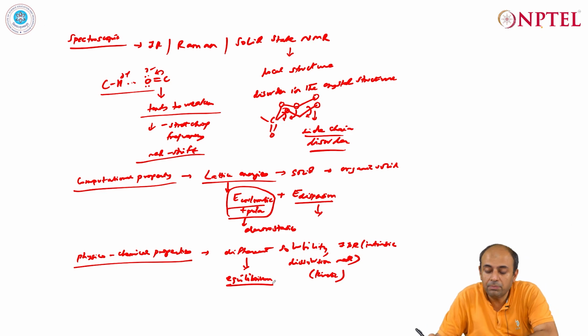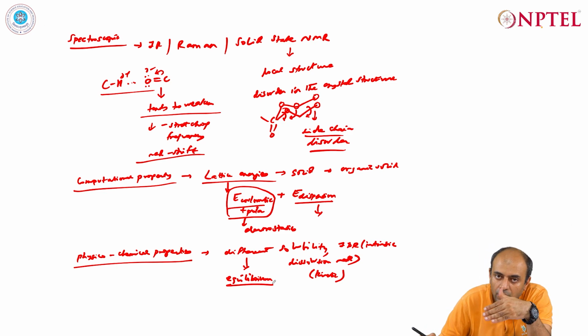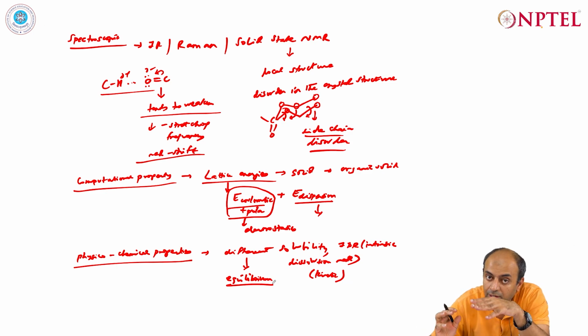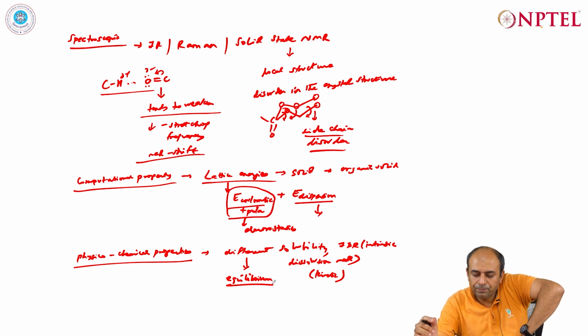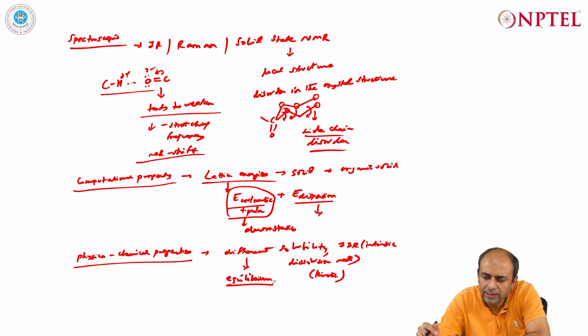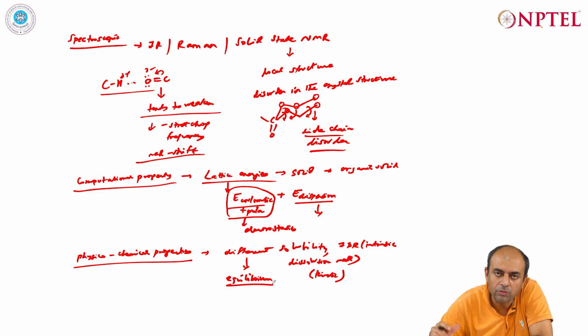So these kinds of experiments can also be done, and it has been observed that the initial rate of dissolution of a polymorph is different, and the solubility for different polymorphs is also going to be different, but the equilibrium solubility is not much affected. There is not much difference in the equilibrium solubility. The differences are not significant. However, the intrinsic dissolution rate can be significantly different for different polymorphs. So these are some of the very interesting ways in which we can characterize the polymorphs.